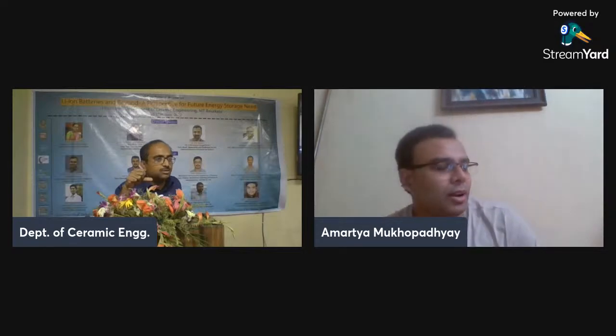Yeah, it is always there. Not as bad as lithium, but sodium is still volatile. So one always has to have a little bit of sodium excess, and that sodium excess also has to be optimized. Second, there is a problem with nickel, because nickel always tries to go to its +2 oxidation state. Unless the stoichiometry is maintained very precisely, the nickel will not be in the desired oxidation state. If there is a little bit of mistake, the nickel will try to go to its +2 oxidation state and come out as nickel oxide. So that is another problem one faces with nickel. So yes, the sodium excess taken to take care of the sodium loss during the high temperature treatment has to be very precise and has to be optimized.